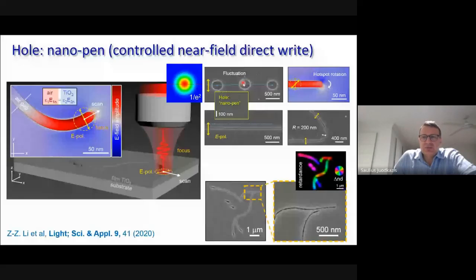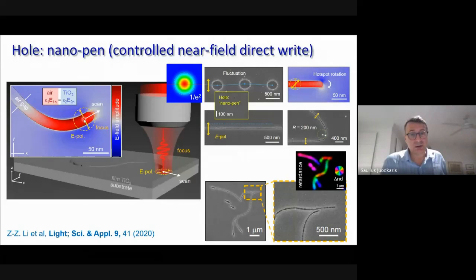It's hundreds of nanometers. But if we are very patient and we choose conditions at the very tip of intensity, here it's my marker pointer here. I'm moving it out just to not block the hole. So if we ablate in 1, 2, 3 pulses, we can really ablate a nanohole of tens of nanometers, and then we reduce pulse energy by 30%. It means it will never ablate anything nearby. But once we are on that goal, exactly for this effect which I just described about continuous permittivity around the interface, we can use it as a pen. We can drive ablation and modification. We can steer it by changing the orientation of polarization, and we can really make nanowriting.